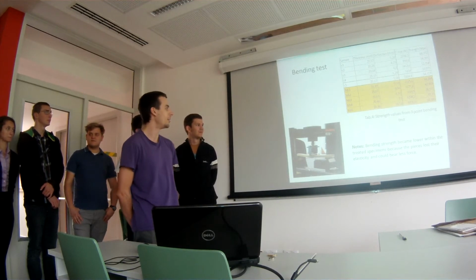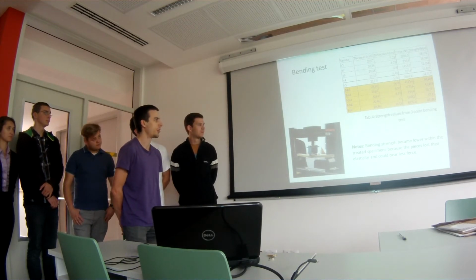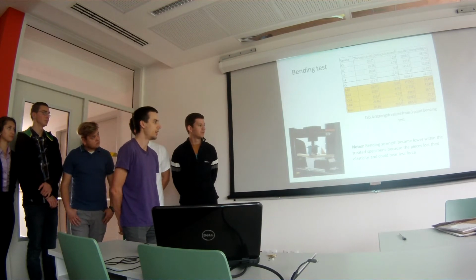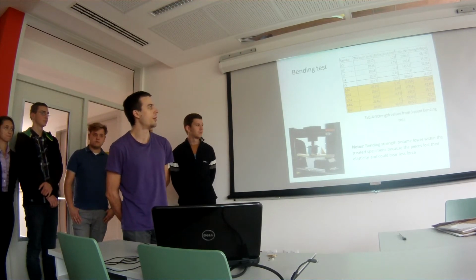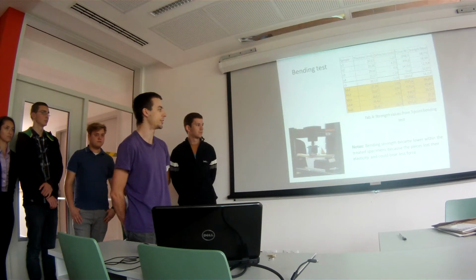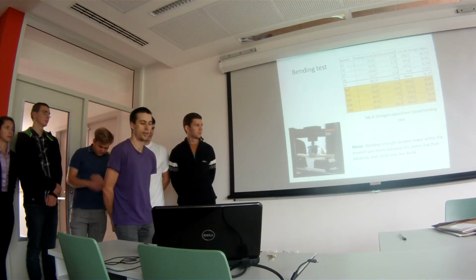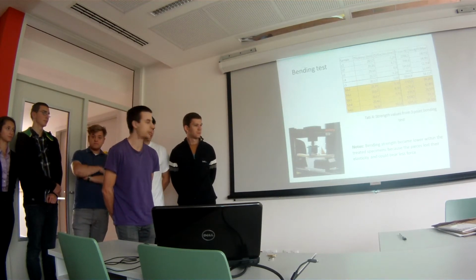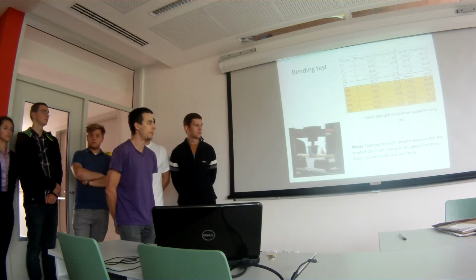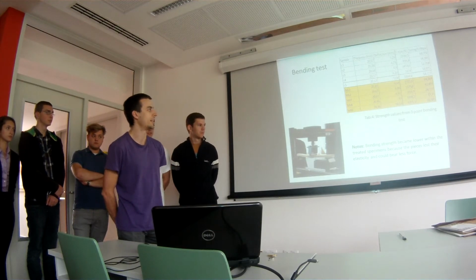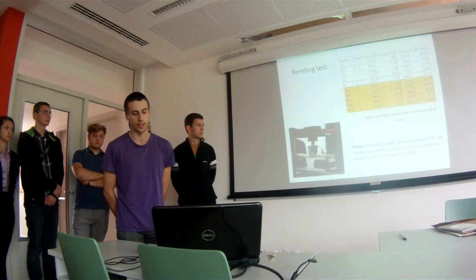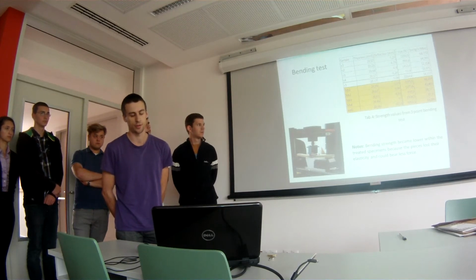So we tested the bending with the 3-point bending test. And we came to the conclusion that because the wood was compressed and the lignin and the other stuff just burned away from the wood, it lost its elasticity, and basically it just breaks more easily than the non-treated ones.